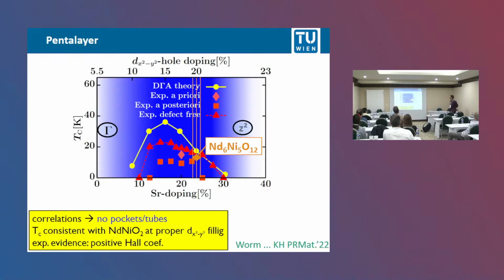So now let's put this data point of the 5-layer film into our phase diagram, and it's 20% doping. You have 3 inequivalent layers, therefore you have a little bit of variance in the doping of the 3 layers, but it's not much. And this data point is nicely in agreement with previous experiments as well as the D-gamma-A calculation. Let me also point out that the 5-layer compound has a positive Hall coefficient.